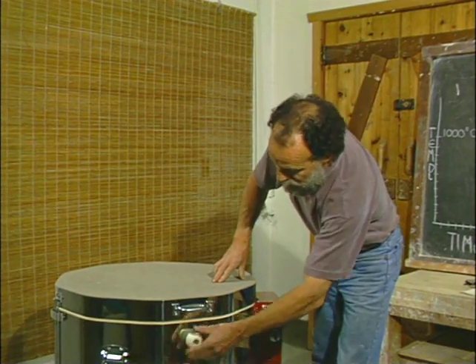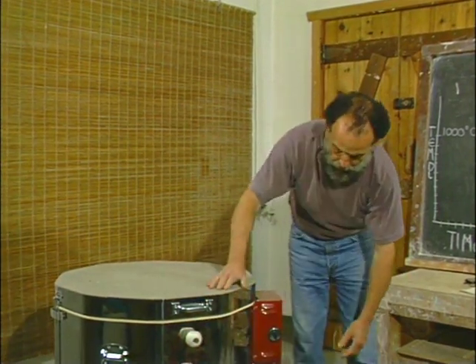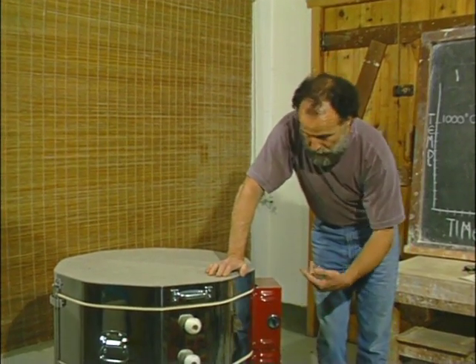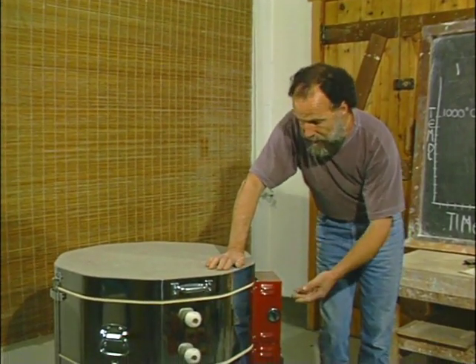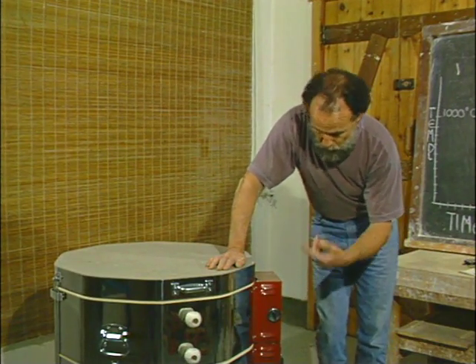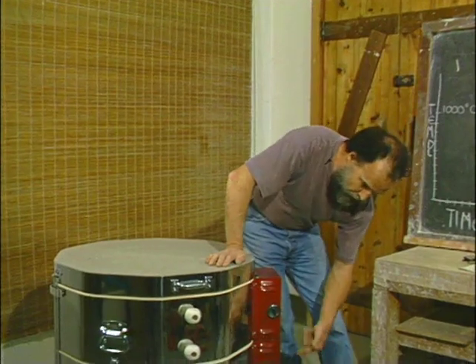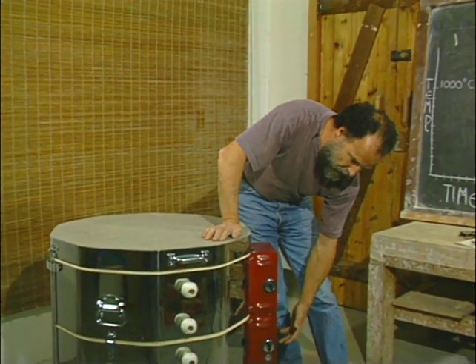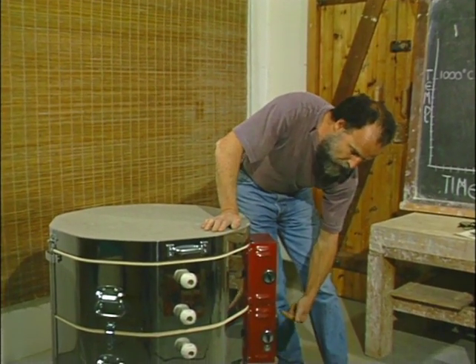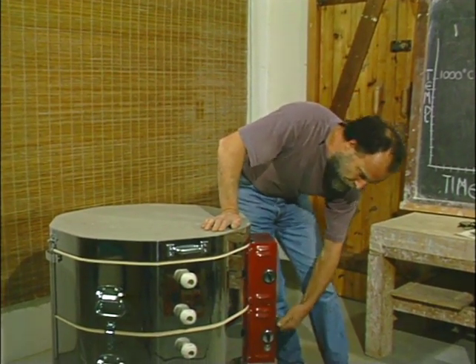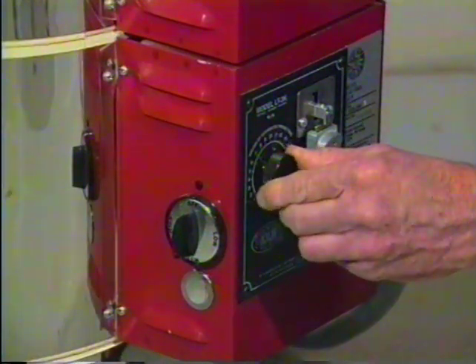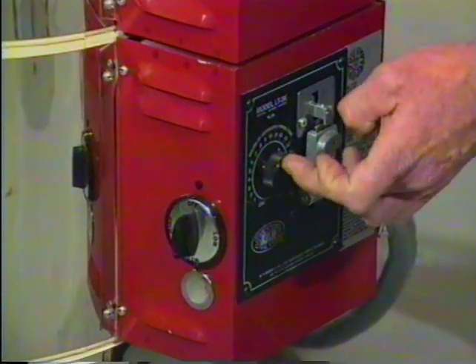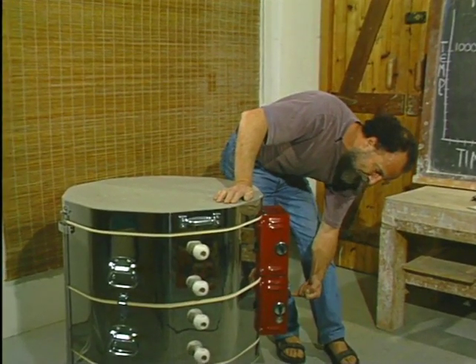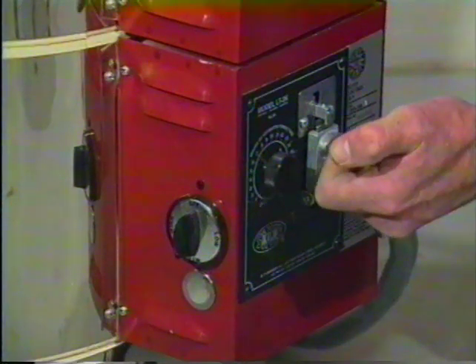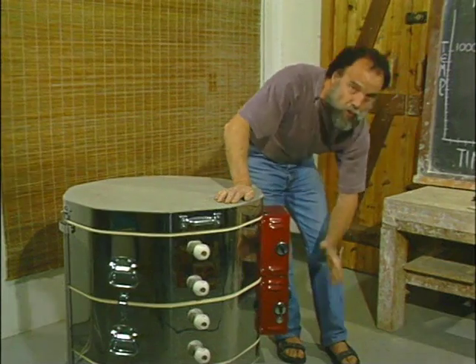Okay, so here we are with the EnviroVent on, all the plug holes in, and we're ready to switch the kiln on. The general principle here is that we've got to advance the temperature fairly slowly. So what we want to do first of all is set the kiln ready to roll with the kiln sitter and the time limit switch. So first of all, let's turn our time limit switch around to 12 hours, which means that after 12 hours, irrespective of what's happened, the kiln will be turned off. Next thing we need to do is to actually arm the sitter by depressing the central button until it engages. Now the kiln's ready to roll.